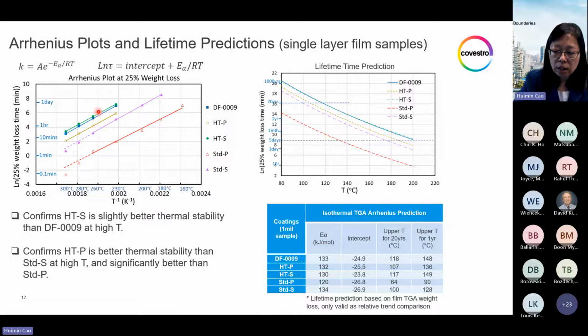As you can see, the HTS performed the best, even slightly better than the DF-0009. And even the HTP still lasted longer than the standard secondary coating and significantly better than the standard primary coating. Based on this study, the lifetime prediction is drawn in this chart. For example, at 140 degrees C, the standard primary only lasted a couple of days, losing 25 weight percent, while the HTP is predicted to last almost a year.